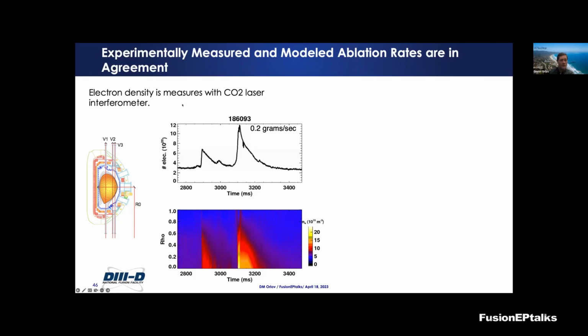We had to rely on something really fast, which is the CO2 laser interferometer. It gives us measurements along 4 chords: 1 mid-plane chord, 3 vertical chords. So I worked with Mike Van Zeeland to inverse the data and try to get an estimate of how many electrons were in the plasma as a function of radius. This plot on the bottom shows the electron density as a function of time and radius.